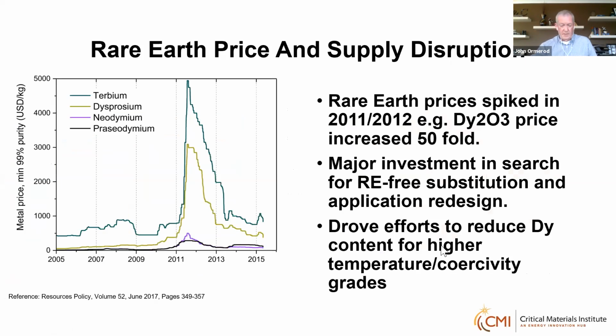Then 2011 and 2012 happened, and rare earth prices essentially went crazy. What we saw obviously was this big spike in price, and particularly dysprosium oxide price increased 50-fold in literally a few weeks. So what happened, there was a major investment made around the world in the search for either rare earth free substitution or efforts to reduce dysprosium content for the higher temperature, higher coercivity grades.